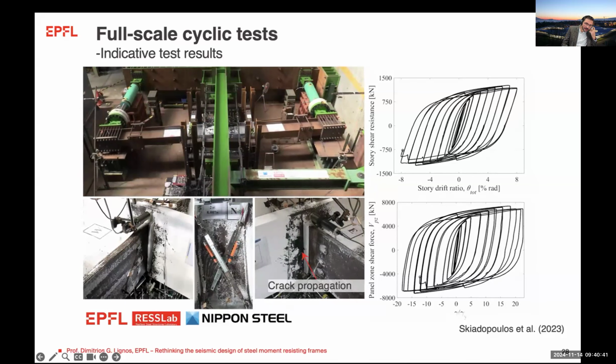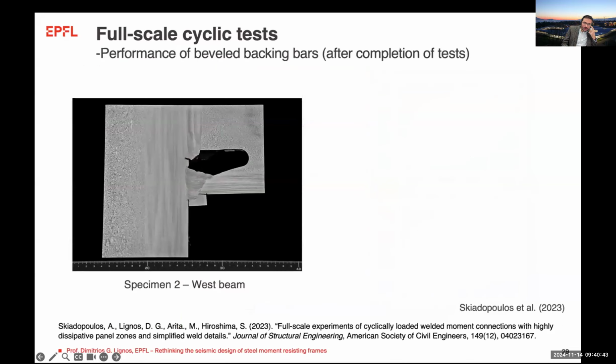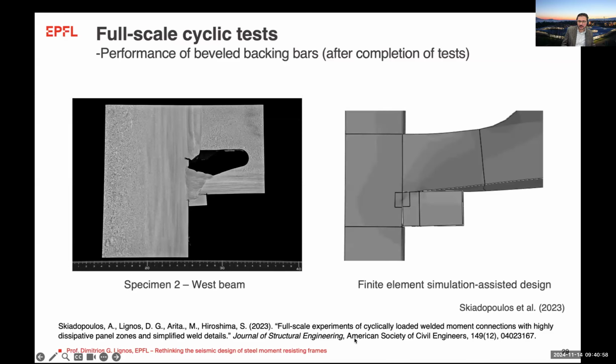So now, if we look at the region around the bevel backing bar, after the completion of the test, you see that I have no indication that cracks initiate in this region. And this matches, in fact, our finite element simulation assisted design, which was encouraging to see when you introduce the bevel in the backing bar.